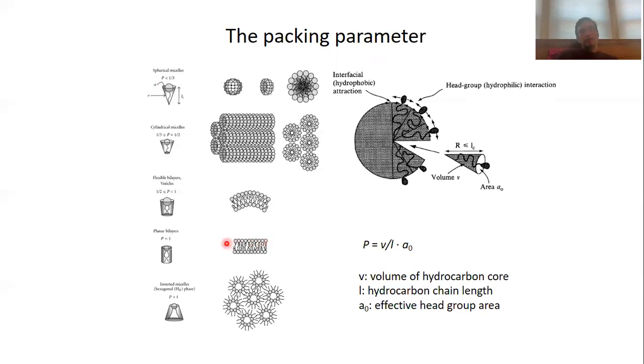The hydrophilic part and the hydrophobic part approximately consume the same space. In this case we can form so-called lamellar structures. So we have layers of silica and planar bilayers of surfactants, and these layers alternate. This is the so-called layered, also called lamellar, mesostructure.